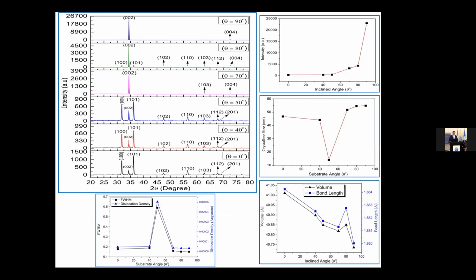Also, this figure shows the XRD results investigated for the different substrate inclined angles. We can see the intensity of the XRD pattern along the (002) peak, which is preferred to the c-axis, which confirms the zinc oxide nanorods are preferred, oriented, and well aligned over the whole range of substrate inclined angles when changing the substrate inclined angle.